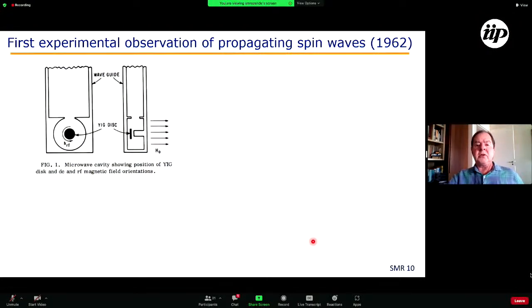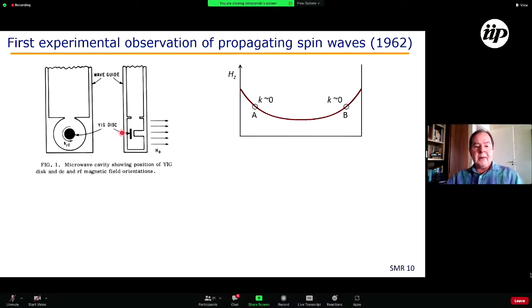Well, the first experimental observation of propagating spin waves was made with YIG in 1962. The author, I'm going to show his paper shortly, used a small disk with a few millimeters in diameter, half millimeter thickness, made of single crystal YIG. YIG is used in these experiments when it's grown in single crystal form, which is not very difficult to do. The magnetic field is applied perpendicular to the disk. This is what we call a re-entrant microwave cavity.